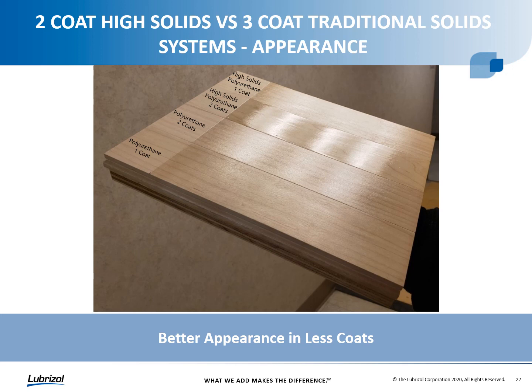Especially when you look at the 2 coat application, you can really see the gloss development of the 2 coat high solids, and the way that the coating pops and really stands out compared to 2 coats of the standard polyurethane, where with that one you might need a 3rd coat or more to develop similar appearance.